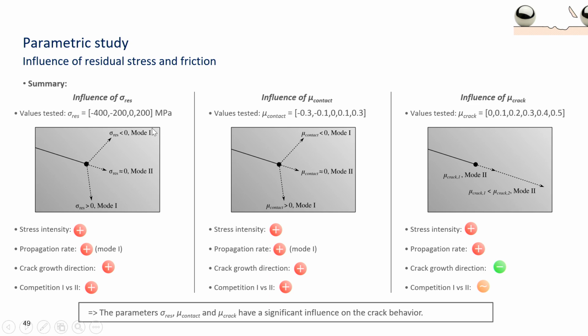Then one of the results is here. This one is very important. When you have compressive residual stresses, because it is negative, the crack will have the tendency to branch towards the surface. Okay? And when you have no residual stresses, it will go straight. And when you have tensile stresses, it will have the tendency to go in depth, like that.